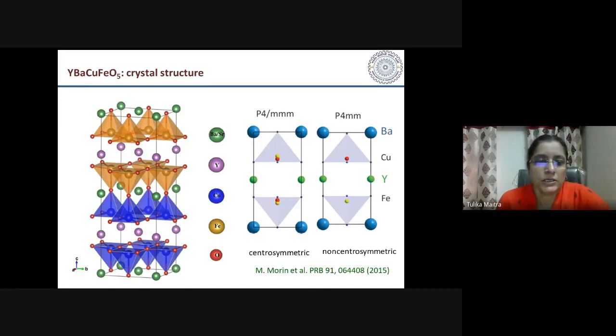So this is the crystal structure of YBaCuFeO5. There are two space groups in the literature for this material. Both space groups give a good fit to experimental measurements, so experiments actually cannot distinguish between these two. In one case the iron and copper share the same site, and in the other case they are separated.